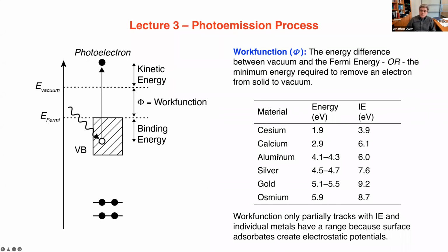So if you have a piece of aluminum foil, for example, it's going to have a coating of aluminum oxide. And if you put it into a photoelectron spectrometer and you measure it, you're going to get a different work function than if you have a freshly cut piece of aluminum or one that's cleaned under vacuum using an electron beam. That aluminum is going to have a very different work function because there's not this oxide layer in the way. Okay, so it turns out the work function of a sample is not necessarily an intrinsic property of the underlying bulk material. It's also modulated by the surface.